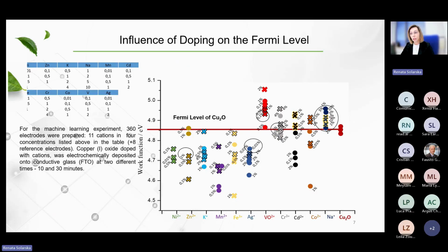And for that reason, we screened a number of dopants. We produced over 360 electrodes with 11 cations at 4 concentrations, and based on the primary screening, we could choose the best dopants to affect the surface properties, since the Fermi level requires the withdrawal of the electron from the surface. So based on the results of these measurements, we could see that zinc, nickel, and other cations are worth further investigation.